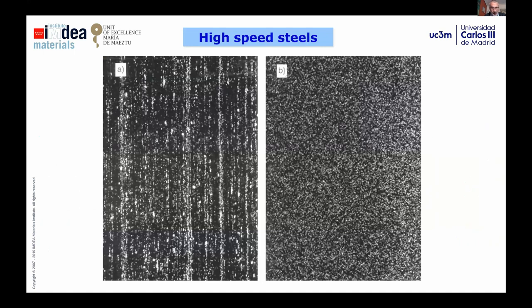High-speed steels can be produced by different ways, by casting, forging, of course, then machining, and so on. On the left, we have a typical forged high-speed steel. If you see the microstructure, you can see in a matrix of iron-based material, you have a lot of the white part of the microstructure are the dispersed carbides. As after forging, we have a directionality of these carbides. The size of the carbides are really high.